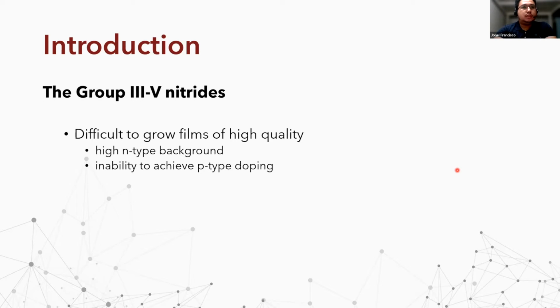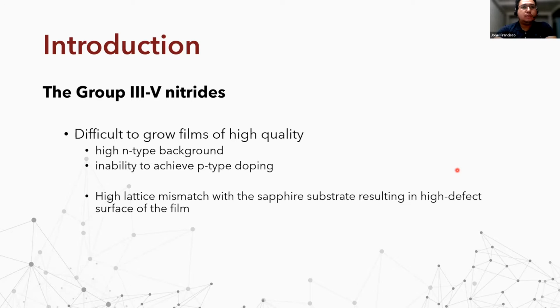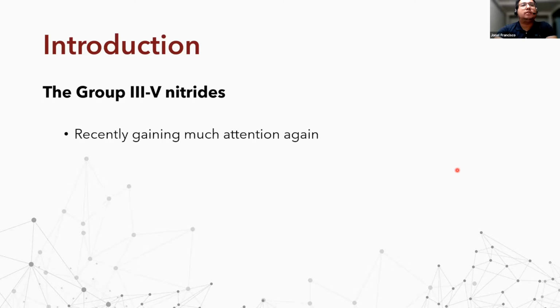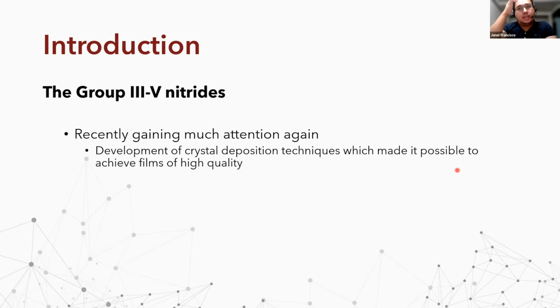This characteristic is attributed to the high lattice mismatch with the sapphire substrate, resulting in high defect density of the surface film. In fact, sapphire and gallium nitride are incommensurate type of epitaxy. That is, there is no direct correlation between the lattice of the substrate and the thin film. Fortunately, it is again recently gaining attention due to rapid development of crystal deposition techniques, which made it possible to achieve films of high quality.